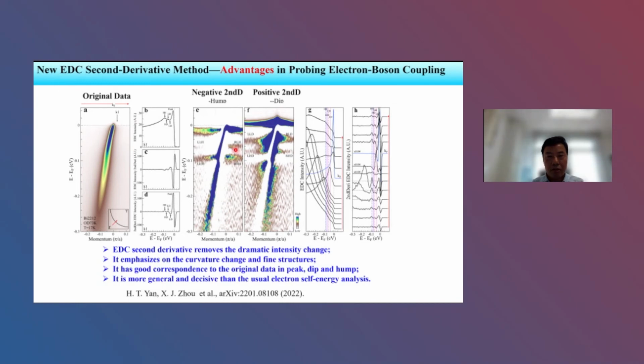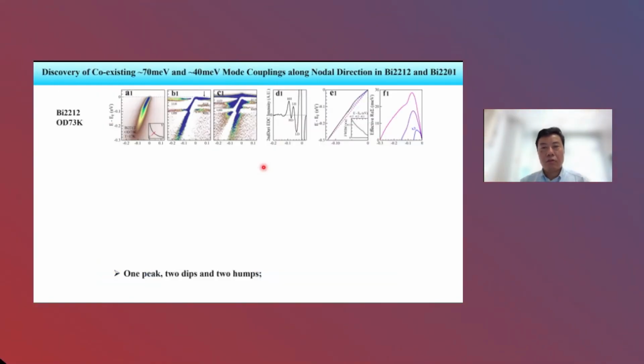That means there are two mode couplings here. By this way, we first measure along the nodal direction, the real original data here. We do a second derivative and see the two flat bands here. Okay, so this is a Bi2212 overdoped, Tc 73 Kelvin data.